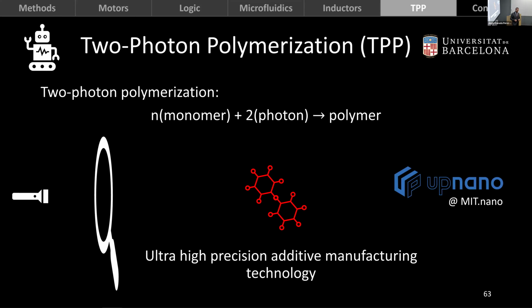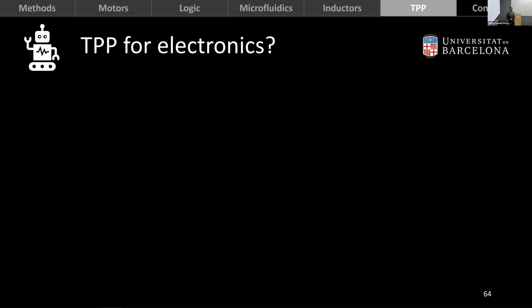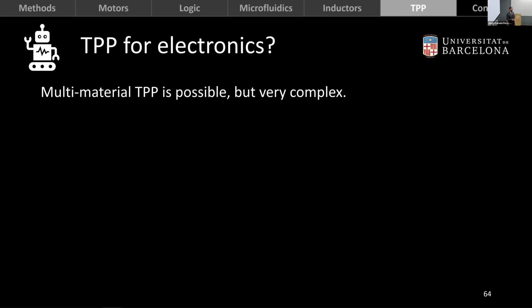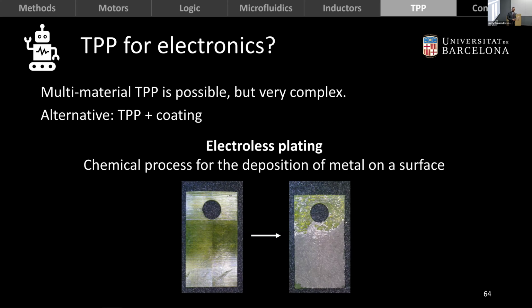And right, so now can we use this for making electronics? Well, for that we need to somehow throw metal into the equation. One way to do that is through multi-material TPP, which is possible, but extremely complex. So the alternative way that we looked into is combining TPP with a coating process. The particular strategy that we used is electroless plating, which is a chemical process for the deposition of metal on a surface. Basically, we start with this polymer part, and we end up with the same part covered in metal.